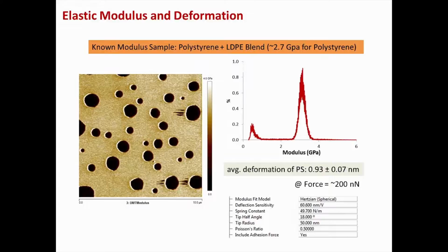Now, how do we make sure that the measurements we are doing are right and it is reporting the right modulus numbers? So Bruker also has some known modulus samples, like polystyrene with an LDPE blend. Polystyrene is known to have a modulus of about 2.7 GPa. So what you do is reference the tip, or calibrate the tip, from these samples and measure the elastic modulus on them.